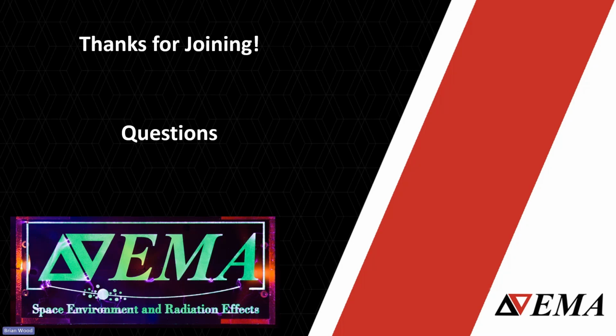So I didn't really have a slide for that, but we are continuously developing added capabilities, whether it's new standalone things or something to enhance the capability of the main test chamber. One of the standalones is not totally related to space environment testing, but it's laser-induced damage threshold testing. This goes along with the optical testing we're able to do. Essentially, it's a capability to measure how much energy from a laser pulse it takes to start to deform a coating or a lens that's given to us. This is a common test that's part of an optical characterization suite.